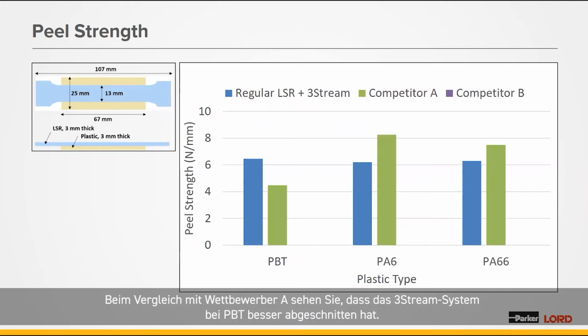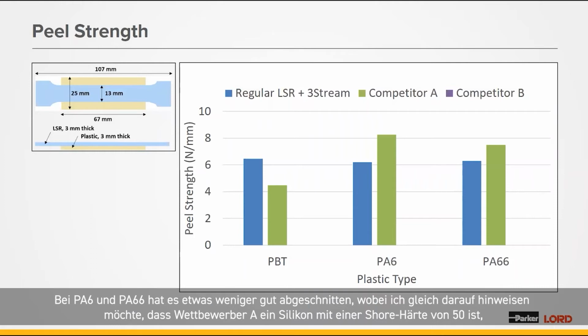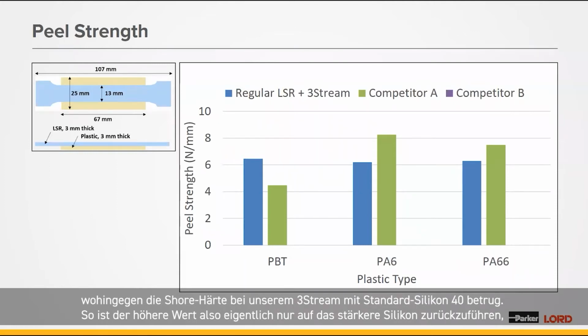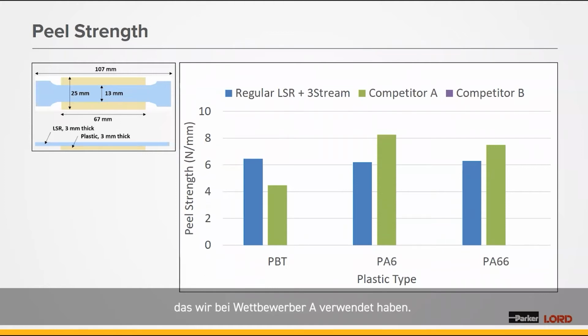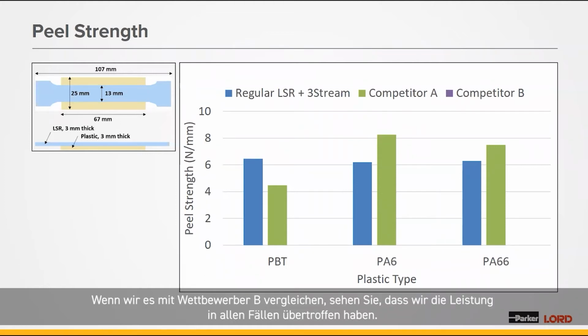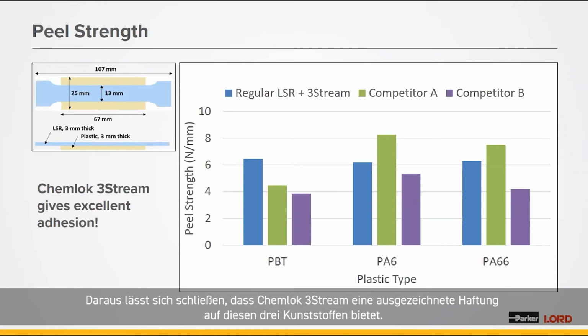When we look at that compared to competitor A, what you see is that the 3-stream system performed better on PBT. On PA6 and PA66, you can see we were a little bit less, but I will point out that competitor A is a 50 durometer silicone versus the regular silicone that we used, which was 40 durometer with 3-stream. So the higher value is actually due to just the stronger silicone that we use for competitor A. When you compare it to competitor B, you can see that we've exceeded the performance in all cases. So the bottom line is Chemlok 3-stream gives excellent adhesion on these 3 plastics.